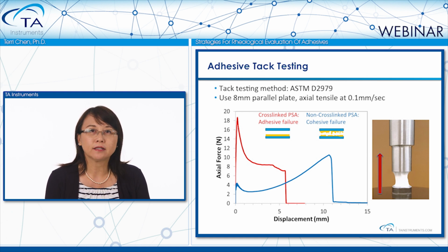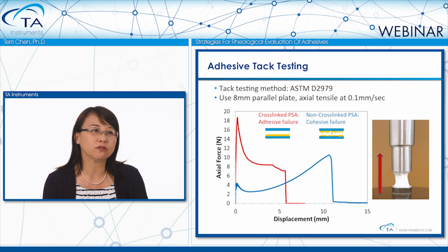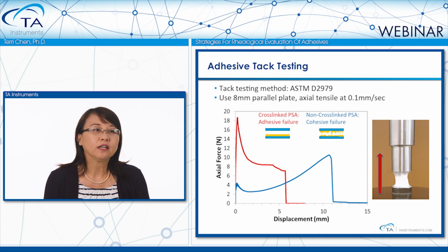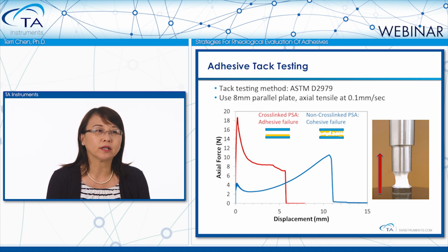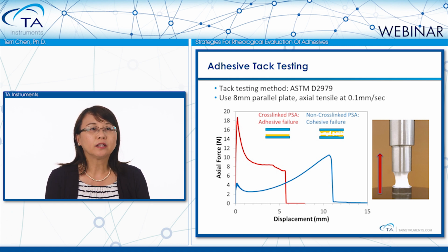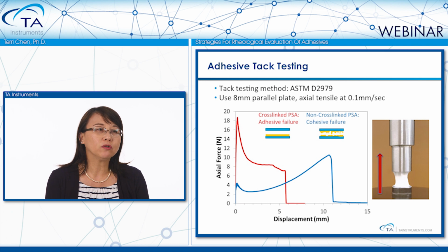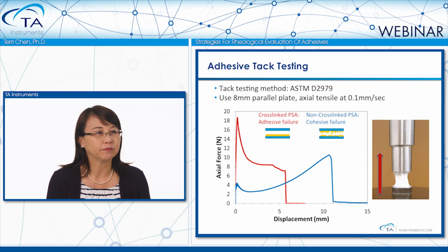In this type of test, breaking may occur in 3 different ways. If the bond force at the interface is stronger than the cohesion strength of the adhesive, breakage will occur between adhesive layers. If the cohesion strength is much stronger than the adhesion bond at the interface, then breakage will occur at the plate interface. Sometimes there will be a mixed breakage of both cohesion and adhesion.